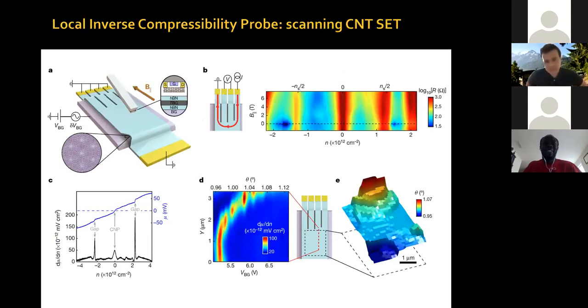So the experiment that we did is the following. The group of Shahal Ilani has developed this wonderful technique with a scanning single electron transistor. He has a short segment of a carbon nanotube. This carbon nanotube at low temperature acts as a single electron transistor, or as a quantum dot. Basically, it's a very, very sensitive voltage detector, an electric field detector. So you can place this carbon nanotube at the apex of a tip, and you can scan this tip above a device, in this case, a Magic Angle Graphene device.